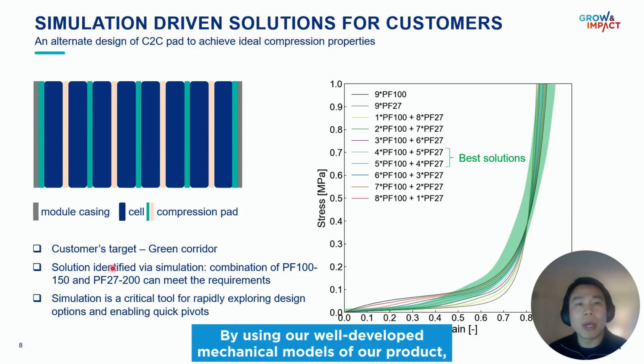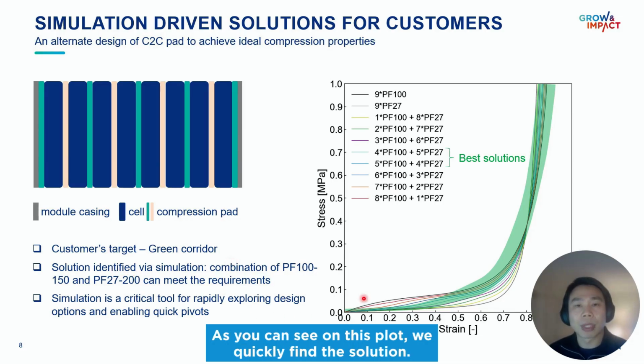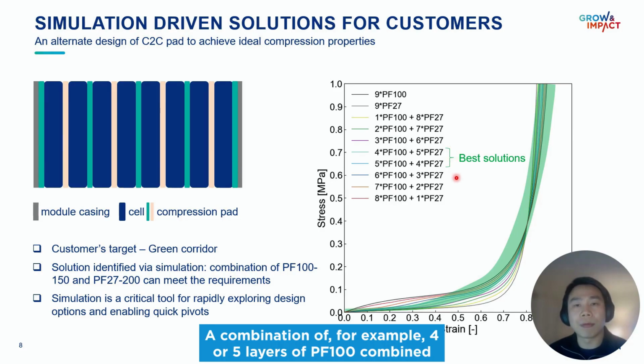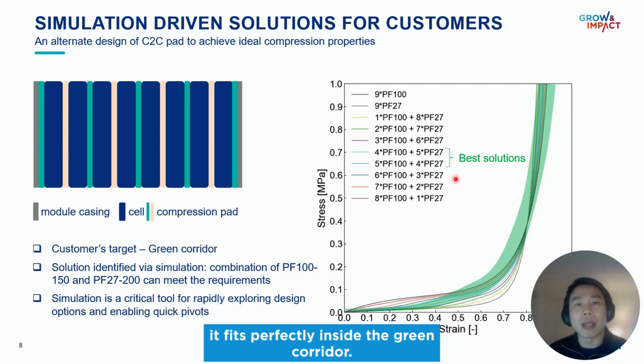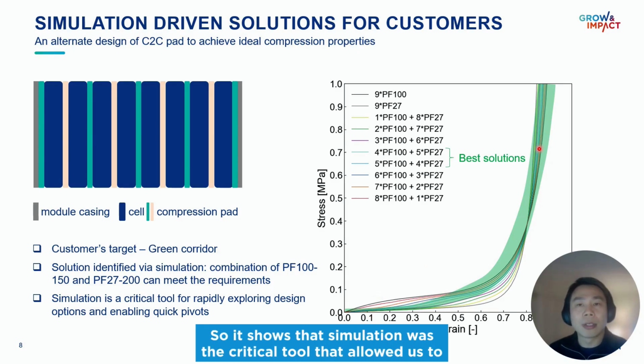By using our well-developed mechanical models of our product, we simulate various combinations of these two foams. As you can see on this plot, we quickly find the solution. A combination of, for example, 4 or 5 layers of PF100 combined with the corresponding layers of PF27 fits perfectly inside the green corridor. So it shows that simulation was the critical tool that allowed us to find this customized solution very quickly.